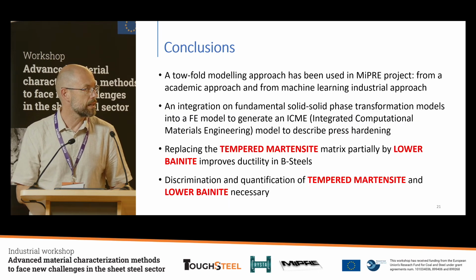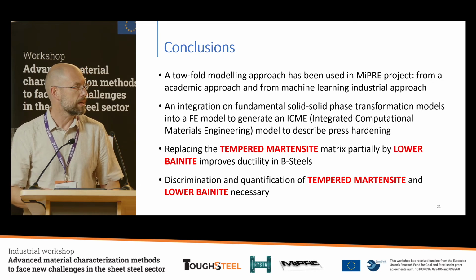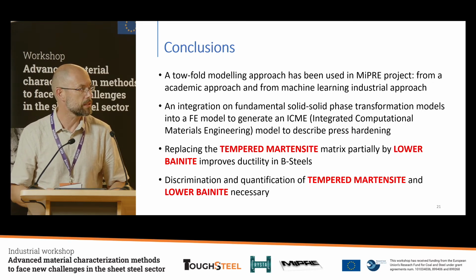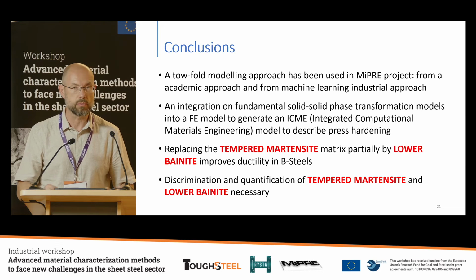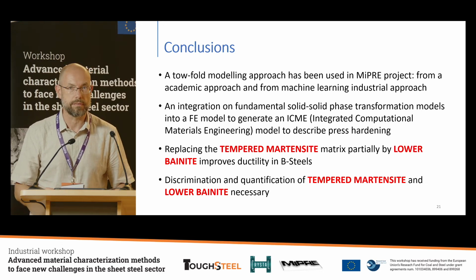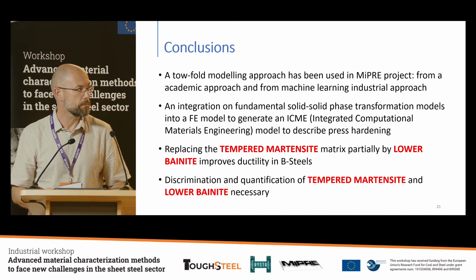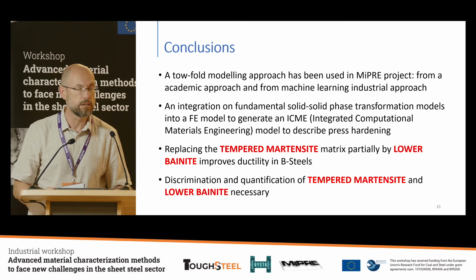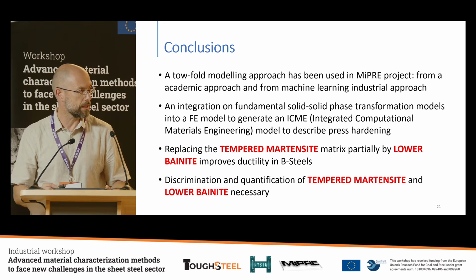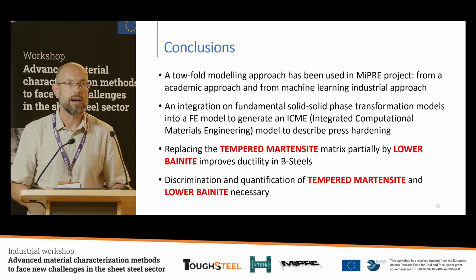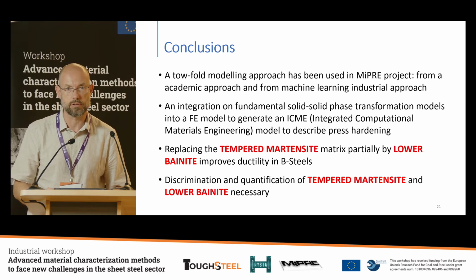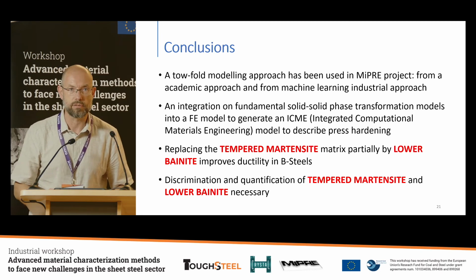And this is basically the conclusion that I will draw from this talk. I don't want to only highlight some part of the project, but regarding the whole project, there is a two-fold modeling approach that we use in MIPRE, from an academic approach and machine learning, combining both, and an integration of fundamental solid-solid phase transformation models. We want to generate an ICME computational model to describe the press hardening. Regarding the role of the microstructure, replacing tempered martensite partially by lower bainite looks to improve the boron steels without losing significant strength. Discriminating and quantifying tempered martensite and lower bainite is very difficult, and we still need to do a lot of work to find a quick method to do that. But thank you very much for your attention and I am open for questions.